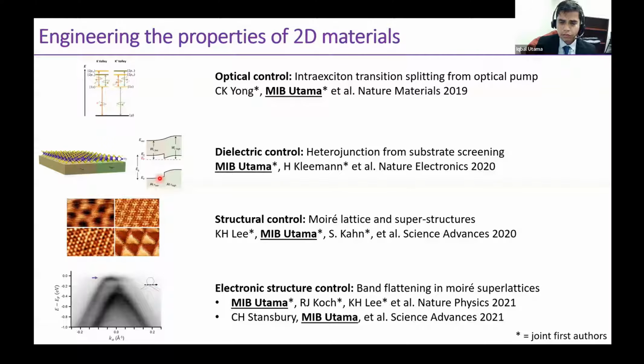In addition, because of their van der Waals nature, the bonds in the out-of-plane direction of the material are saturated, so you relax the requirement of lattice matching and the need for registry of the atoms in the out-of-plane direction, so that you can introduce some kind of twisting between the different layers. As a result, you can form a so-called interference fringe that is now called the Moire lattice. We then developed and implemented a scanning probe microscopy imaging technique that images the microwave impedance of the sample, so that we can view these nanoscale Moire fringes in the sample.